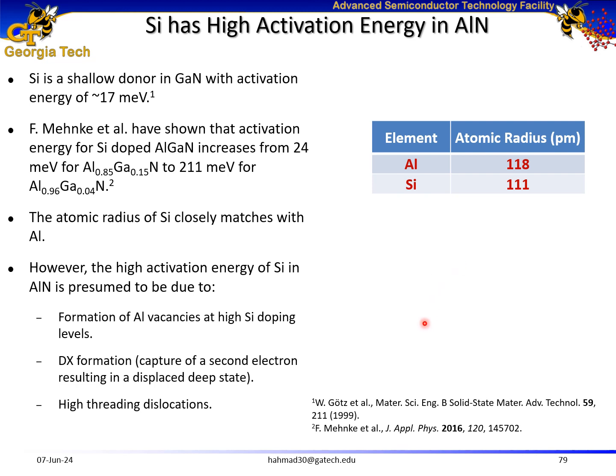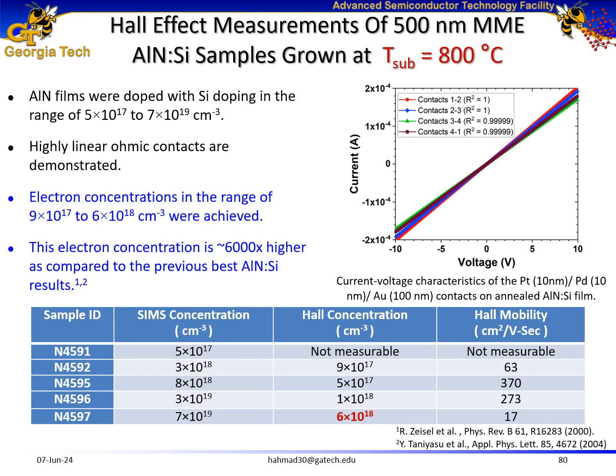Silicon, we know that is a shallow donor in gallium nitride with activation energy of 17 millielectron volts. However, with increase in aluminum content in aluminum gallium nitride, its activation energy increases to above 200 millielectron volts. So although the atomic radius of silicon closely matches with aluminum in aluminum nitride, due to several reasons, for example, formation of aluminum vacancies, DX formation, which is transition of silicon from shallow to deeper states, and threading dislocations, the activation energy of silicon in aluminum nitride is high.